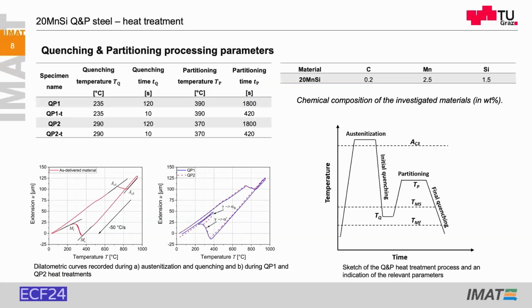Yeah, the first steel, 20 manganese silicon, quenched and partitioned. Probably you have heard about partitioning, meaning that you cool, you quench down between martensitic start and finish, and you do an additional partitioning step to stabilize the retained austenite and to gain some bainitic ferrite. Here we did a physical simulation of this heat treatment in the dilatometer.